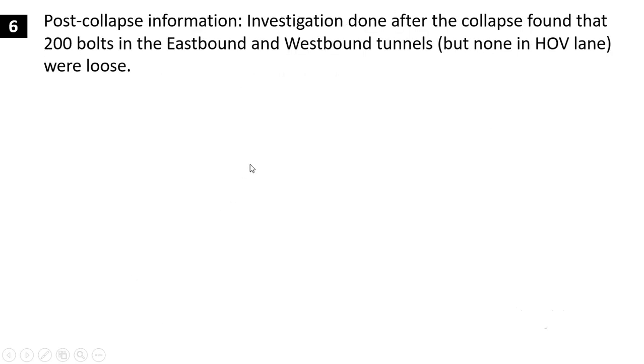Post-collapse information. Investigation done after the collapse found that 200 bolts in the eastbound and westbound tunnels were loose, but none in the HOV lane. So in the HOV lane, the bolts gave quite good performance, whereas in the eastbound and westbound tunnels, 200 bolts were found to be loose, and the accident happened in one of these tunnels.